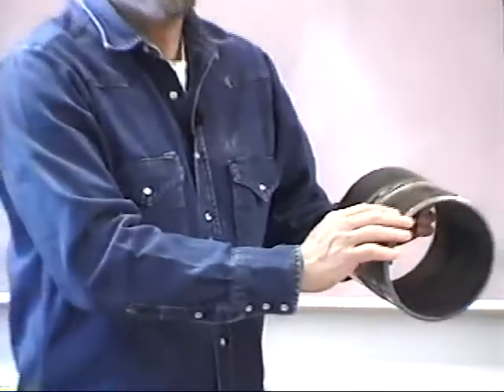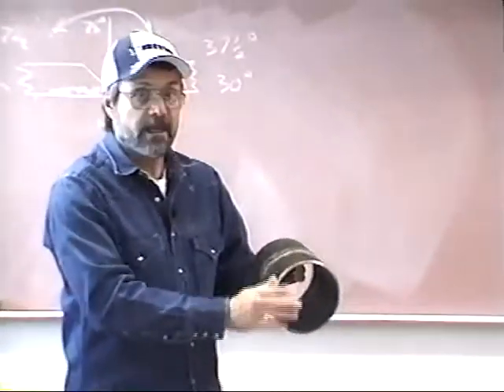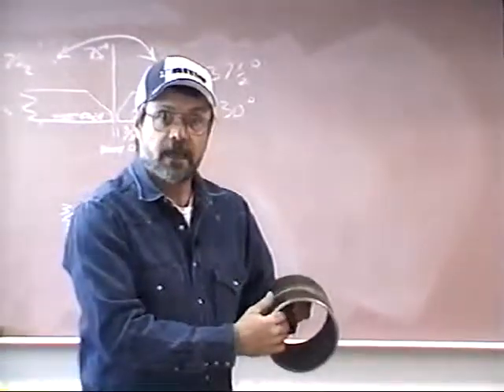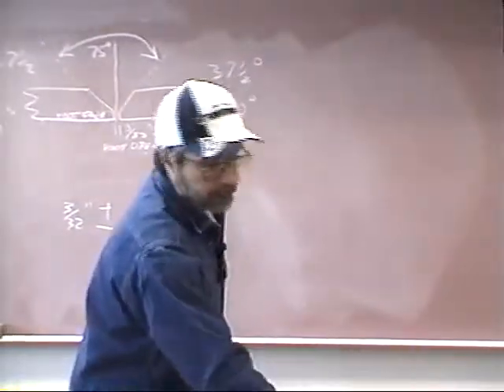And then you're going to want to go around the outside also and clean this back at least a half an inch. And most recommendations are 1 inch, so you don't suck any of this mill scale or coating or paint or grease or anything else into the weld that can cause porosity.